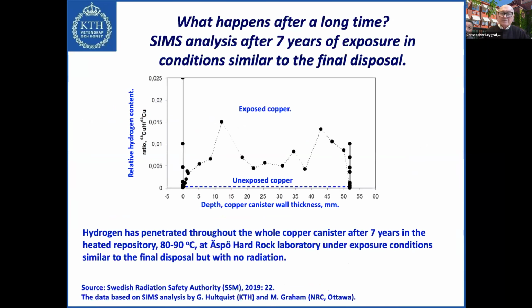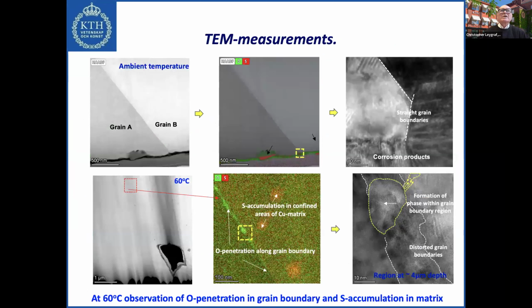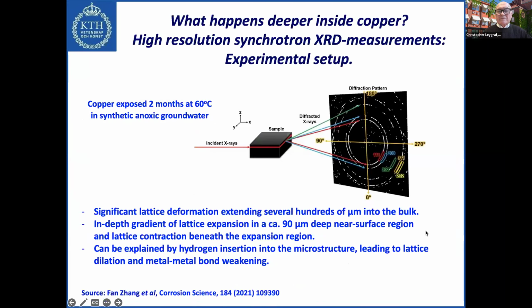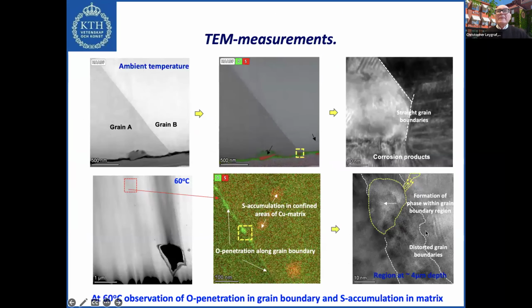This is because of the... Here we are. Again, if you compare the difference in results between room temperature or ambient temperature, you see these very straight grain boundaries at room temperature, and you see these very distorted grain boundaries at 60 degrees. And we see also by TEM that there is a much higher concentration of defects at 60 degrees. So all these defects facilitate the transport of sulfur and hydrogen deeper into the material. So it's really a result of the microstructural changes that occur during the exposure at 60 degrees, which does not occur at room temperature. So this is the explanation as far as we can say it right now.